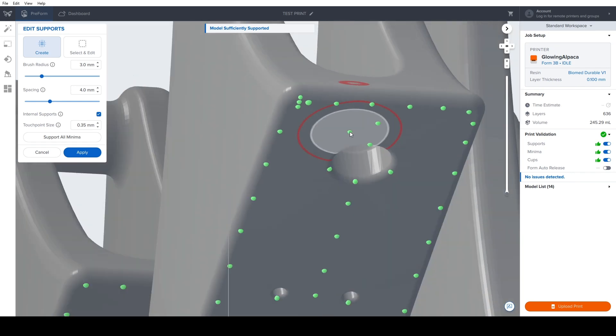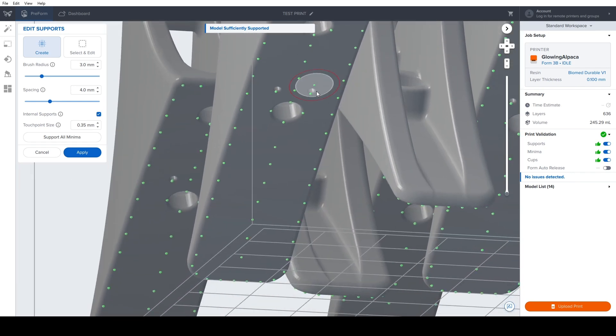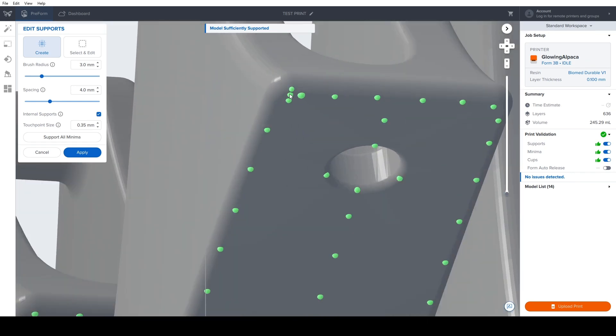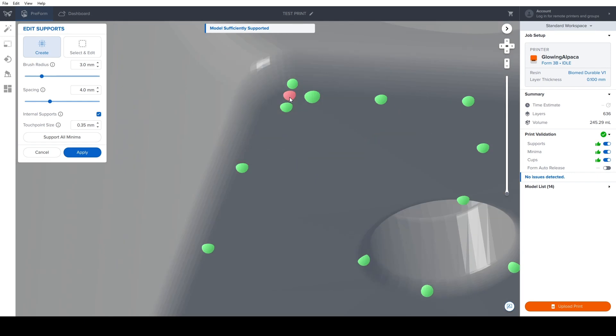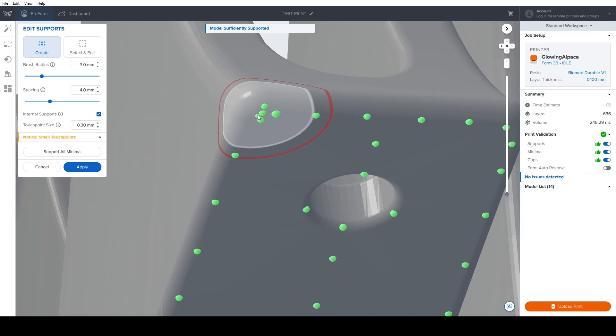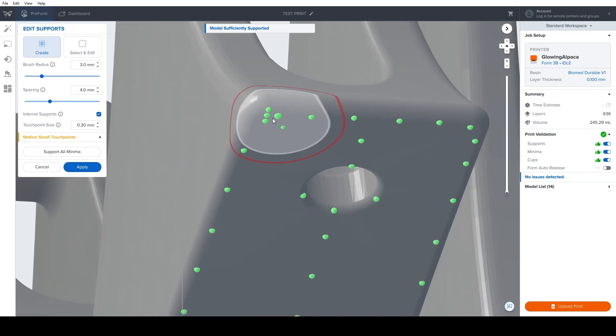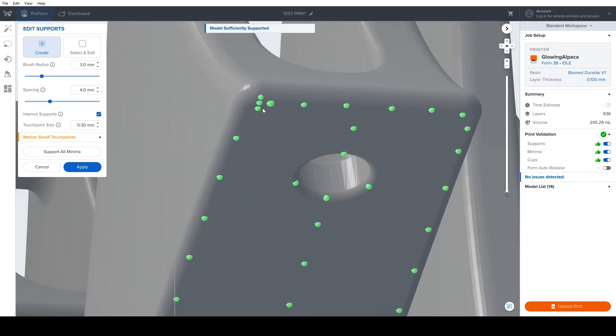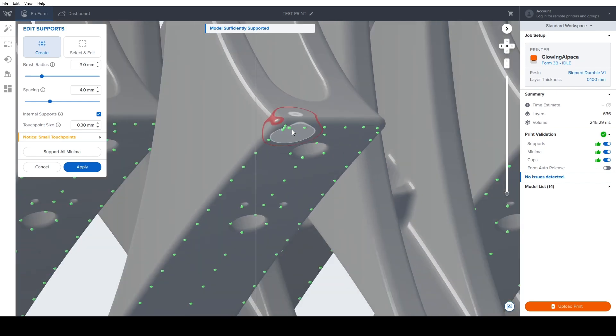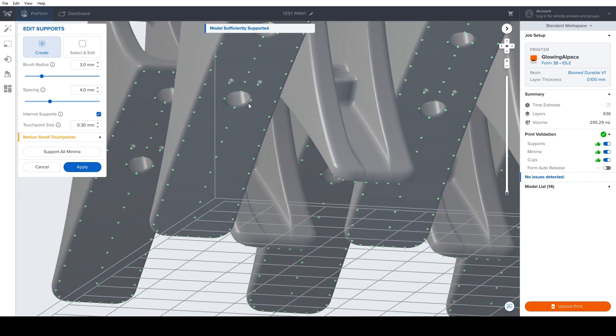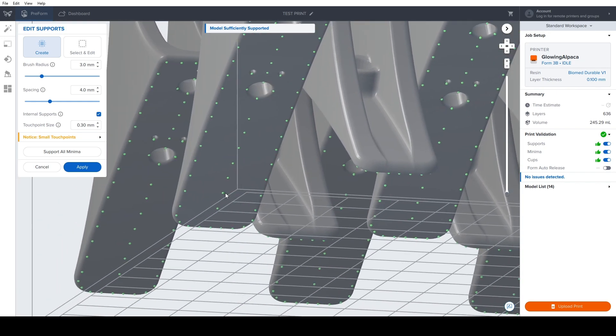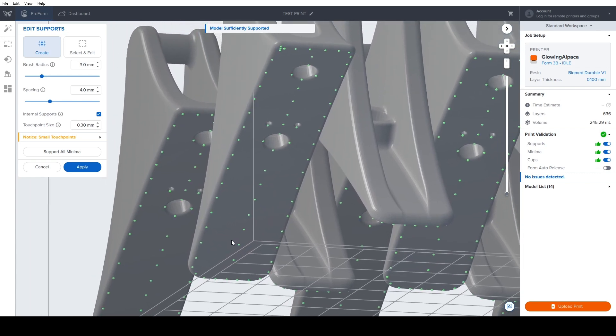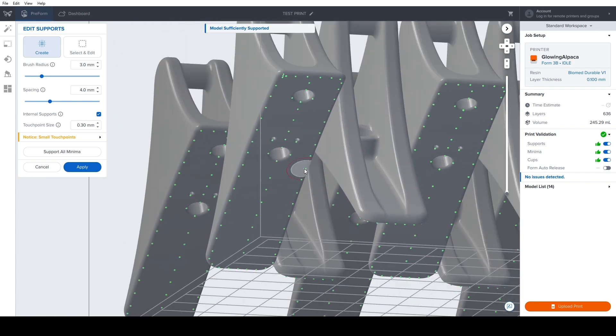We didn't choose to do that for this model, just because we're doing this in a production capacity. And we do want to make sure that success rates are pretty high. I definitely have gone down to 0.3 millimeters for durables and for tough resins. So much smaller than what the default suggests, and you can still have very high success rates. You just need to know and understand where supports need to be and how many supports need to go onto your part.